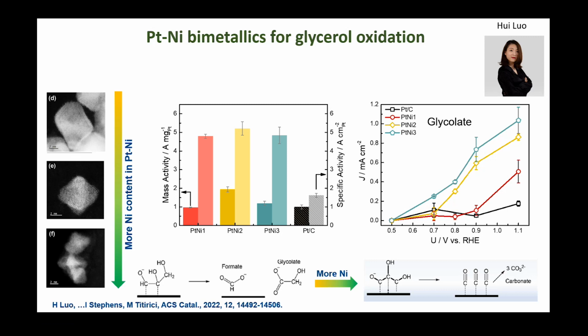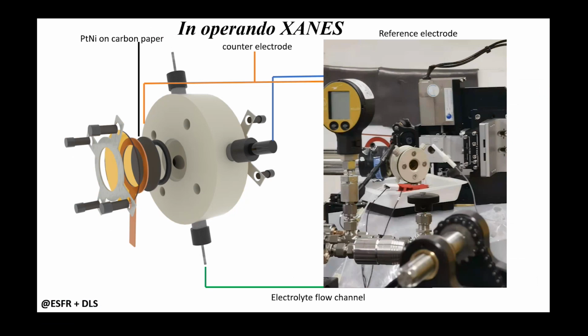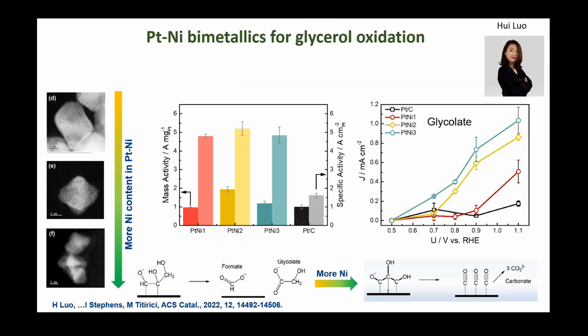And you would see here the selectivity to glycolate, where you would see that the higher the nickel content, depending on the potential, you change the selectivity. That's because of the way these intermediates get adsorbed: the more nickel you have, the more you adsorb them via, let's say, all free carbons, and you get directly to carbonate. So we tried to elucidate the mechanism of this reaction. If you look at this graph here, you would see that it's actually quite advantageous to have one platinum near one nickel, and we have a lot of characterization to prove this, XAS and XPS and ICP-MS and XRD, but I don't have time to show you all of this, but this is published here in this paper.